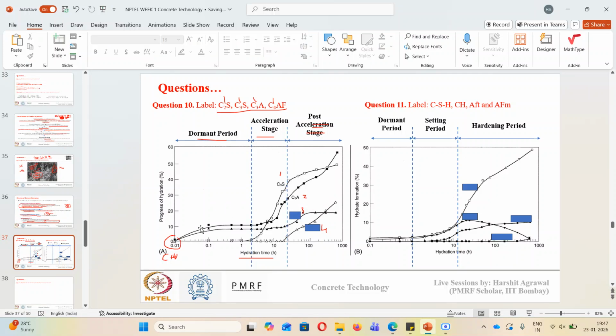Initially C3A reacts with gypsum in the presence of water to form ettringite. Then over time, as gypsum is consumed, ettringite converts into monosulfate. That's why the reaction shoots up again, as C3A reacts with ettringite to form monosulfate.